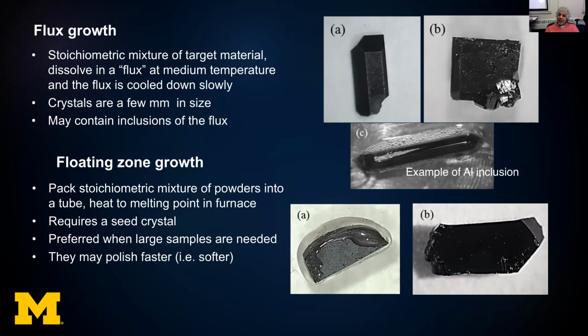The samples that we have, we always polish them and make these structures. Typically, the flux-grown samples are small, a few millimeters in size, and they always have aluminum inclusions. So we have to go to rather thin samples of about 100 microns or so to eliminate all the aluminum inclusions. This is not the case in the floating zone samples. We find them to be polishing much faster, and we have confirmed that some of the floating zone samples are a lot softer, maybe even by a factor of 2 or so, which is an indication that the samples might have off-stoichiometry.